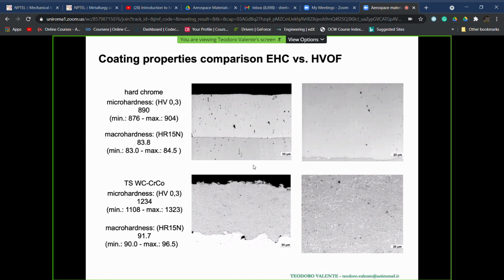And here you have two examples of microstructures. This is the hard chromium, and we have a thickness which is around, if you look at this bar, 200 microns. This is the case of tungsten carbide with chromium cobalt matrix. And if you see here, apart from the surface morphology, which is different, obviously, because this is electroplated, our coatings made by thermal spraying after fabrication do not need polishing, as the hard chromium does, but we can easily achieve the same thickness.